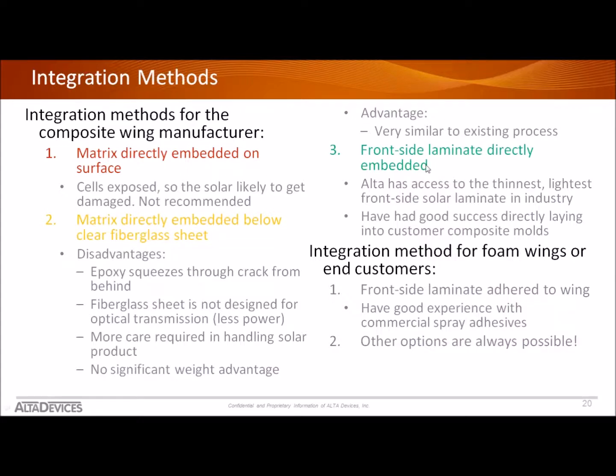So our method of choice is to use a front side laminate, where we use industry standard solar film on the front of the matrix. That would be shipped to you like that, so the front of the solar sheet is protected from minor damage while handling. You then lay that up in your composite mold and then build the wing on top of it. And we've had really great results from aesthetics. You have no surface features that are going to affect your aerodynamics, and you're going to produce really good power because you've got great optical transmission.